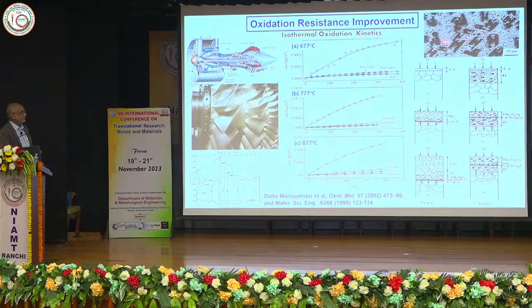So the rest, 15% of the matrix, was interconnected with these intermetallic phases. As a result, if oxygen is invading into the metal and trying to oxidize, it cannot move directly vertically downward - it has to move in a convoluted manner. So you are deferring the oxidation process.